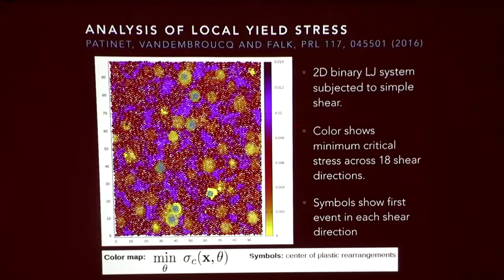So this is the kind of map that Sylvain produces. Here the scale is the local yield stress—how high you have to ramp up the stress on a local region before you get a plastic instability. You can see these yellow regions which have very low local yield stress, and around those, other regions with slightly higher, and then regions with relatively high local yield stress that aren't very deformable. Your eye immediately picks out essentially the length scale of the probe.